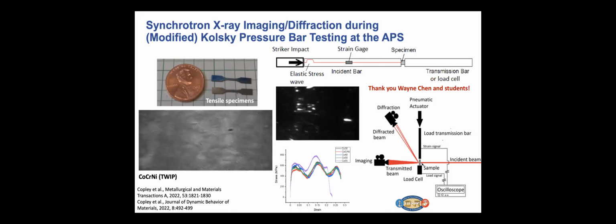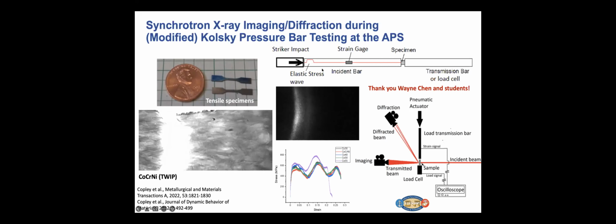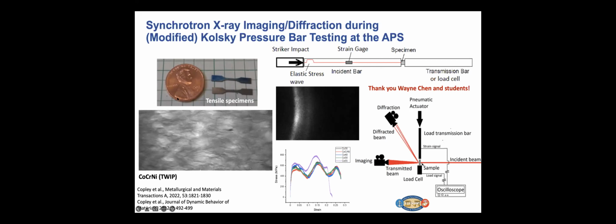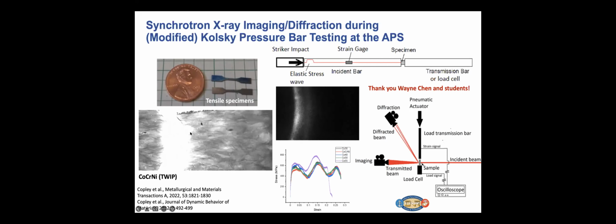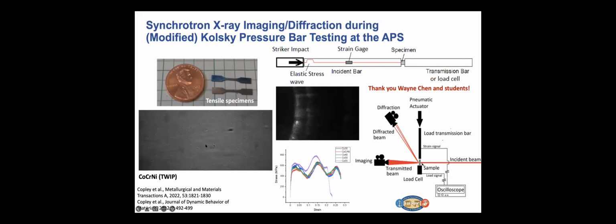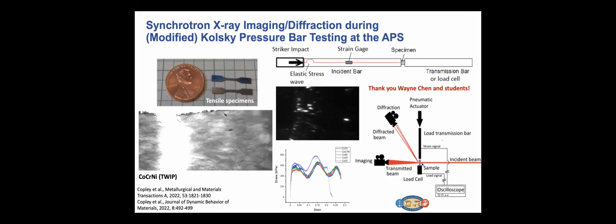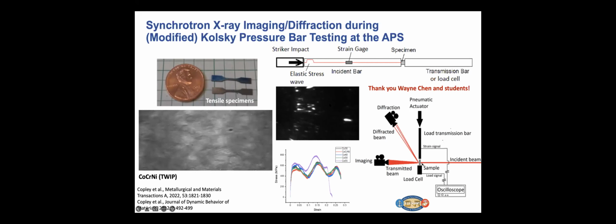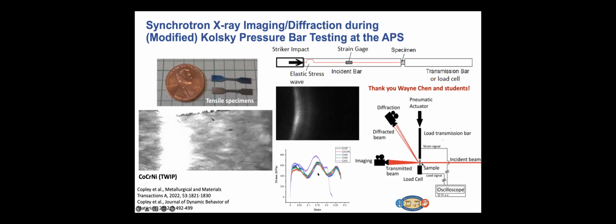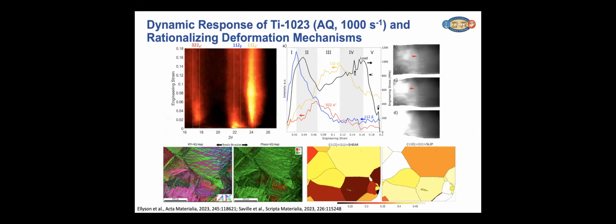So we pursued doing some Kolsky pressure bar testing at the APS, which is schematically shown here. This is a little penny as compared to some of our tensile samples. And down below, we can actually see, this is an example for a cobalt chrome nickel high entropy alloy that undergoes twinning-induced plasticity, but we can see the gauge length being ripped apart, and we can actually see evolution of the microstructure. From these experiments, we can get the diffraction data as well, in addition to the stress-strain response. So this is now an example for our Ti-1023, the as-quench condition, strained at 1,000 per second while we're doing real-time diffraction.